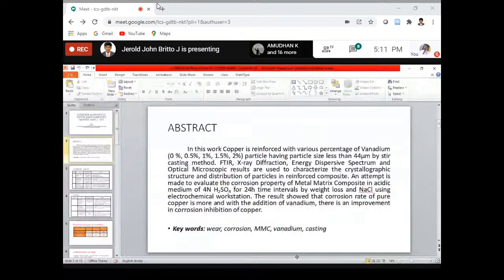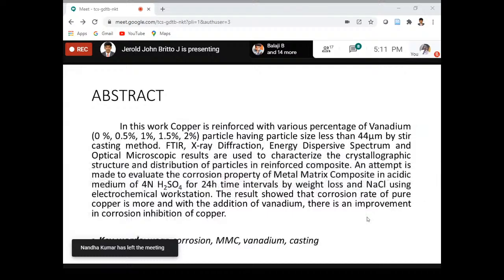Regarding the abstract, in this work copper is used as the main matrix, and vanadium with various percentages like 0%, 0.5, 1, 1.5, 2% has been used. It is reinforced with the primary copper. After producing it by stir casting, we have taken various characterizations like FESEM, XRD, and optical microscopy. In addition, we have also done corrosion testing by both the electrochemical workstation as well as the weight loss method. We have come to a conclusion that with the addition of vanadium, it has inhibited the rate of corrosion.